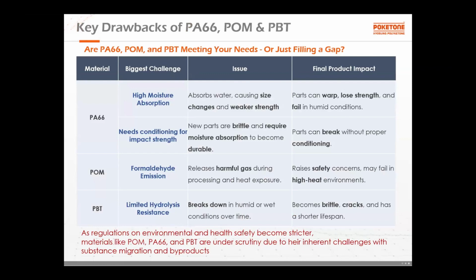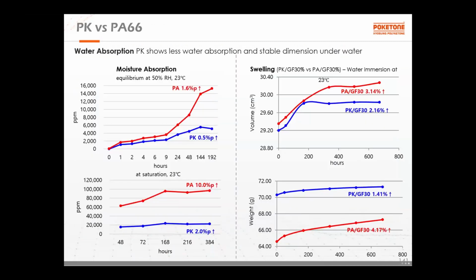As a summary, nylon has high moisture absorption and needs conditioning for impact strength. POM has formaldehyde emission plus low acid chemical resistance, which is not so good. And PBT has limited hydrolysis resistance and thin-wall processing is tricky. As a specific data comparison, polyketone versus nylon 6,6, unfilled and glass fiber 30%, both show polyketone is more stable than nylon, with less water absorption, and after water exposure the mechanical property change is much more stable than nylon.